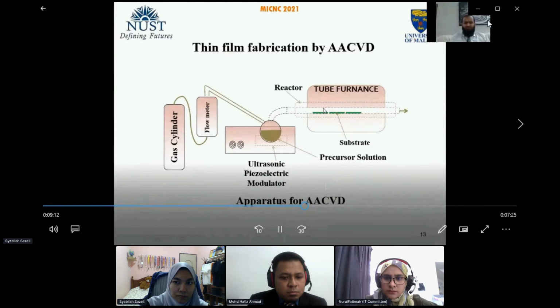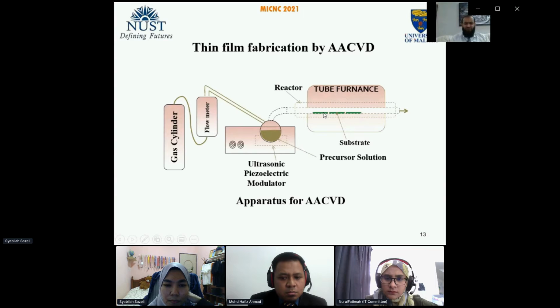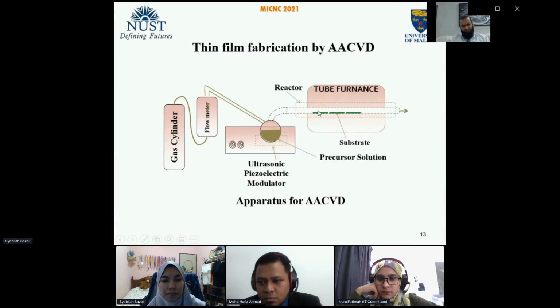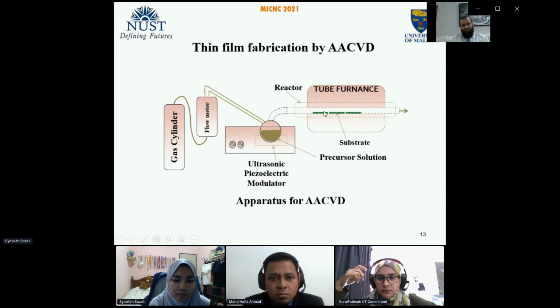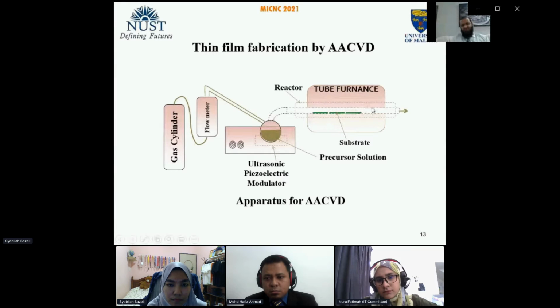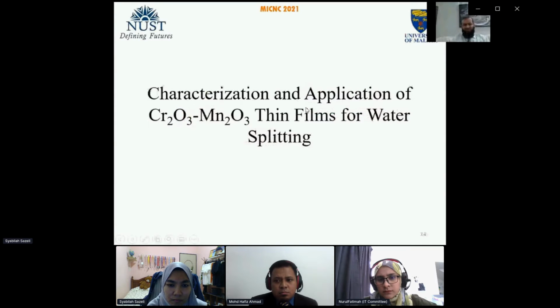The high temperature, above 400 degrees centigrade, decomposes the precursor into oxides. These oxides settle down on the substrate like FTO glass, ITO glass, or any other metal can be used as a substrate. These aerosols are just decomposed into metal oxide. Metal oxide is deposited as thin films, and the rest of the volatile material escapes from this exit. This is a very simple technique, and it was utilized for the preparation of chromium oxide, manganese oxide composite thin film.